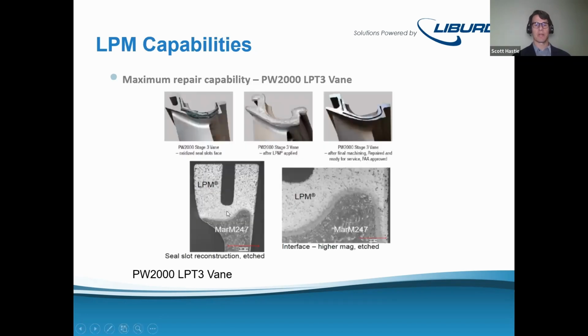So this is the part we saw these two pictures of earlier on. The one thing that I missed highlighting is this gorgeous interface between the LPM and the MAR-M 247 material, etched up so that you see no porosity or no deleterious phases. Here this is where we're starting with an oxidized seal slot face. And what we haven't shown you in this group of 3 pictures is that when we prep this, we're going to open up all of these seal slots that are here and remove some material from this wall. And then we're going to build it up with the putty material.